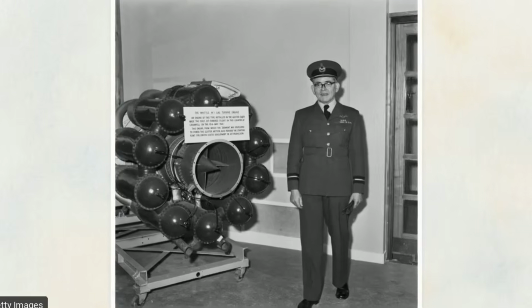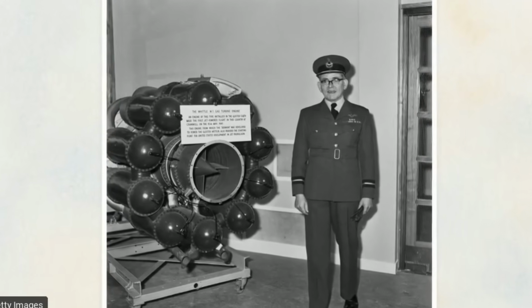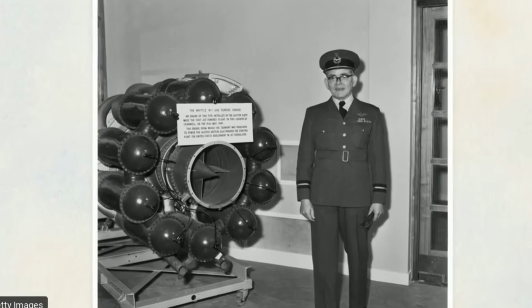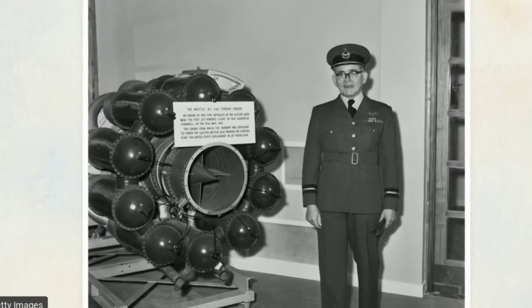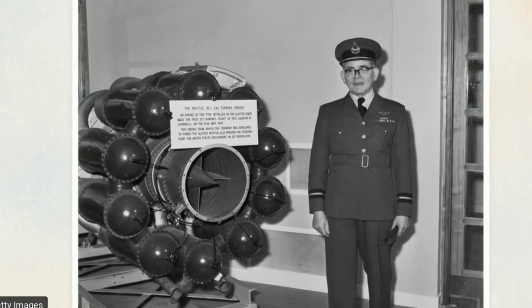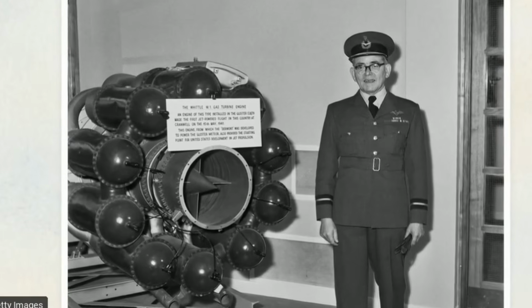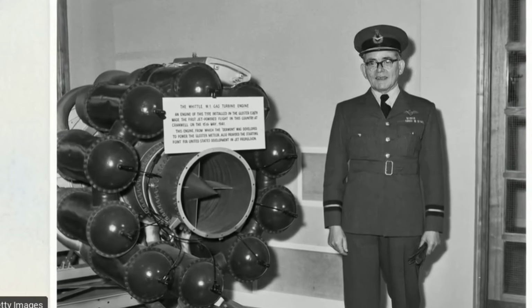We push our engines this hard because the alternative is highly inefficient. Early jet engines from the 1940s ran at much lower temperatures and could barely fly for 10 hours before their internal components began to fail. Mastering this single piece of metal allowed planes to fly further, carry vastly more weight, and burn far less fuel.